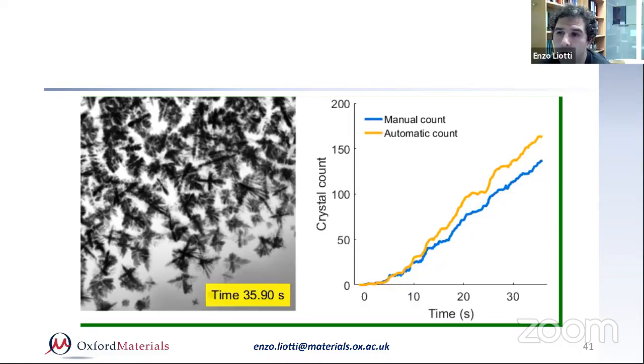No, you're right. The alloy was basically a small bulk sample that we prepared, and then we sliced and polished thin slices. So the alloy is pre-made. You're right, the flow in these conditions can simulate, let's say, some ideal state. When you have flow in one direction or another, it's semi 3D in the sense that you don't have the third dimension because of the thickness. If you want that, you should go to tomography, so it's 3D.